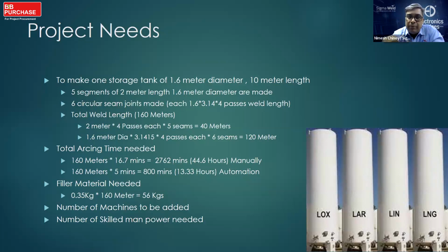And for the circular seam, 1.6 meter dia, it would consume 1.6 into 3.15 into 4 passes each into 6 seams, giving 120 meters. So total length of about 160 meters. Manually welding, this would take close to about 44.6 hours to do. And if you do it with automation, it would take you about 13.33 hours. So this is the difference you will get.